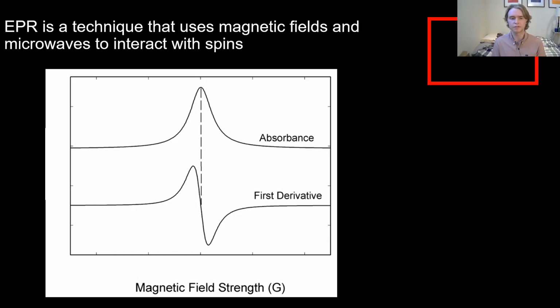So on the x-axis, you'll see magnetic field strength, and then on the y-axis, you'll see nothing here. In most cases, you'll just see intensity. It doesn't actually have a unit there, and it's not particularly useful, except in the case of this quantitative data collection that I'm interested in, or if you want to compare two different spectra to each other, you could look at the differences between their intensity. So the reason that we have magnetic field strength on the x-axis is because I would do a type of EPR called continuous wave EPR. And this is a very common type of EPR to do. And the way that continuous wave EPR works is that while continuously beaming the sample with a particular power of microwave, we vary the magnetic field strength from low to high, and it generates this first derivative curve.